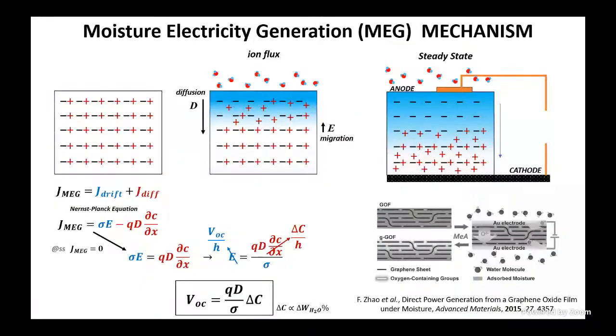This is very briefly the mechanism of this technology. In here, we have the material with the protons, which are bound to the backbone of the polymer or the graphene that contains the oxygen. When this material absorbs water, the protons dissociate, and then we have two different effects here for the ion flux, right? We have diffusion from the higher concentration to lower concentration, and we have migration, which compensate a little bit the diffusion, although this one is more significant. If we can maintain a gradient of humidity in the material, for example, by blocking one side of it, then we will reach a steady state. And I cannot go into much detail in 10 minutes to explain this, but well, basically we will generate an electric potential which we can extract.